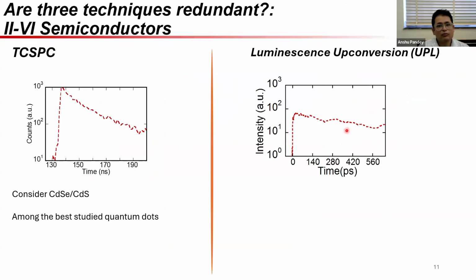Again, there's this criticism which might come up, that these three techniques are redundant and we don't need so many. Well, to set that aside, first of all, let's see what happens with a very well-behaved semiconductor, in this case cadmium selenide, cadmium sulfide. This is among the best studied of quantum dots, and it seems to say that maybe those techniques are redundant, because if we look at TCSPC of these quantum dots, we find that it has poor time resolution, it measures things in nanoseconds, and we get a nice clean exponential trace. If we look at luminescence upconversion, indeed it's measuring shorter times, but it's only measuring the early time dynamics here. So it's effectively a blow up of this part.